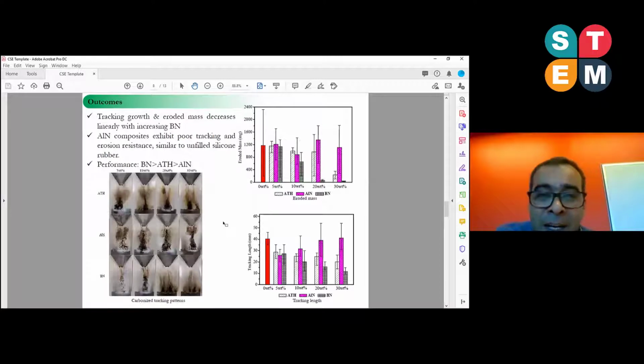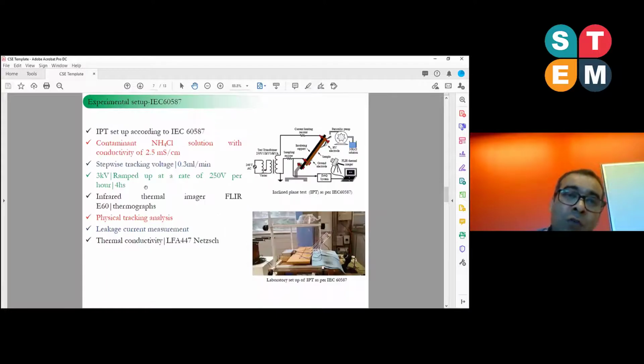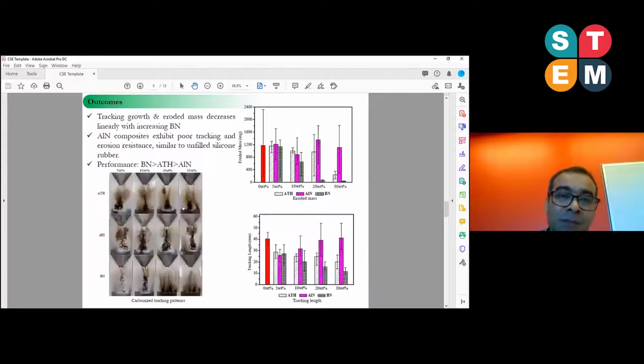So here are the outcomes. It is a total 4-hour experiment. In the initial hour, we start the experiment with 3 kV, and the contamination solution flow rate is 0.3 milliliter per minute. Then every hour we ramp up the voltage by 250 volts. So the total experiment lasts for 4 hours. At the end of the experiment, that is the situation of the samples with 3 different additives.